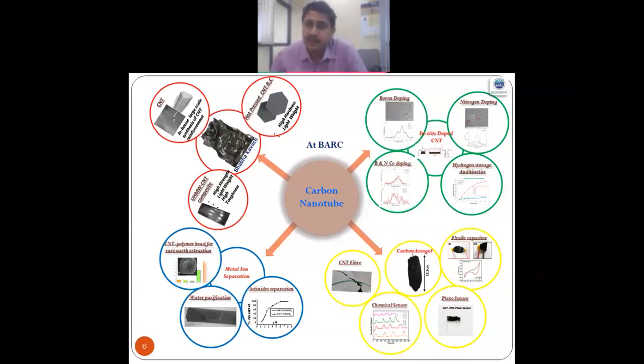Then we are also doping carbon nanotubes with heteroatoms like nitrogen and boron, or co-doping nitrogen and boron, for hydrogen adsorption studies, and we are measuring the kinetics of adsorption. Similarly, we have used carbon nanotubes for metal ion separation, like in carbon nanotube polymer beads for rare earth extraction, and carbon nanotube freestanding tubes for water purification, in actinide separation. And then there is a special 3D form of carbon called carbon aerogel, where the carbon nanotubes are long enough to self-assemble and give a 3D structure, and from carbon aerogel we can make flexible capacitors, piezo sensor, chemical sensor, and also carbon nanotube fiber. So these are the aspects where we are utilizing carbon nanotube.